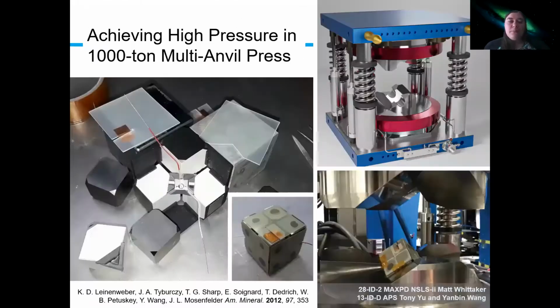So our approach for this was using high pressure, which, as Allison mentioned, is perhaps not surprising given the purpose of these talks, or the context of these talks. But for these experiments, since I was interested particularly in the recovery of these materials, I chose to use a multi-anvil press. And one of the hallmark features of the multi-anvil press is that it allows us to scale this reaction up to much larger volumes.